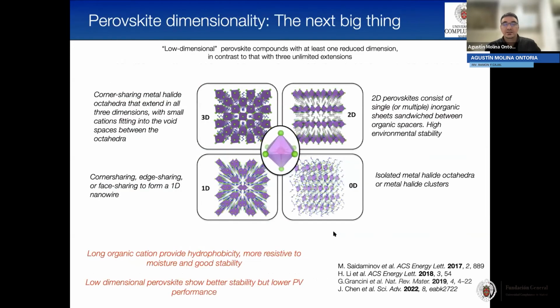What is this? In perovskite, we can reduce the dimensionality by adding longer or bulkier organic cations. For example, we have these 3D perovskites that are corner-sharing metal halide octahedra that extend in all 3 dimensions. If we introduce bulkier or longer organic cations, we can reduce the dimension and obtain 2D perovskites that consist of a single or multiple inorganic sheets that are in between. Then we have the organic spacers.